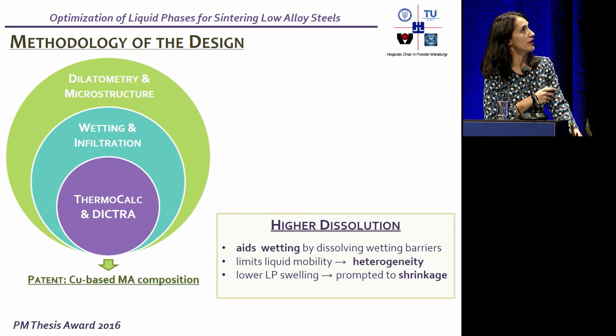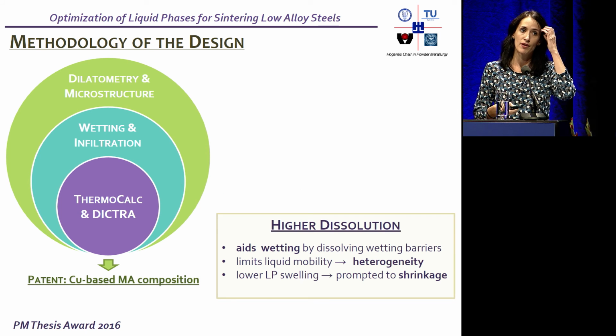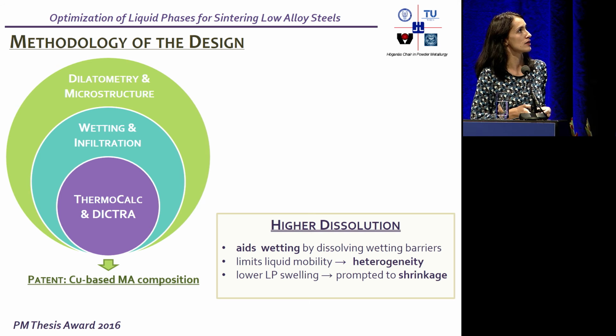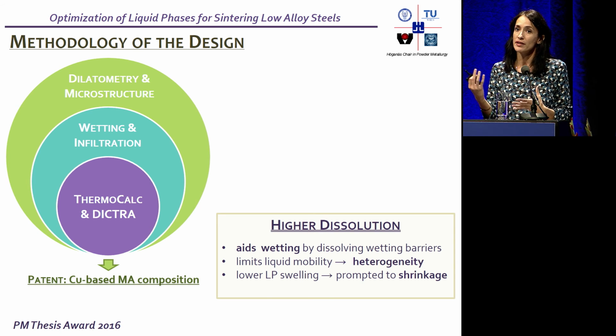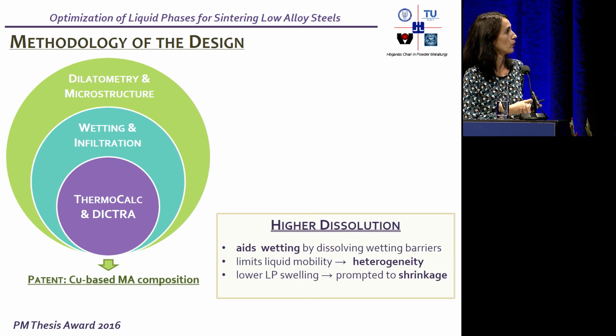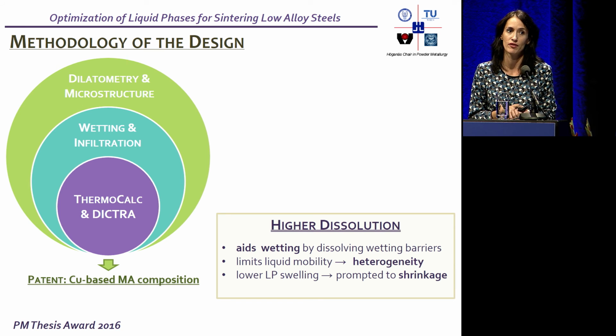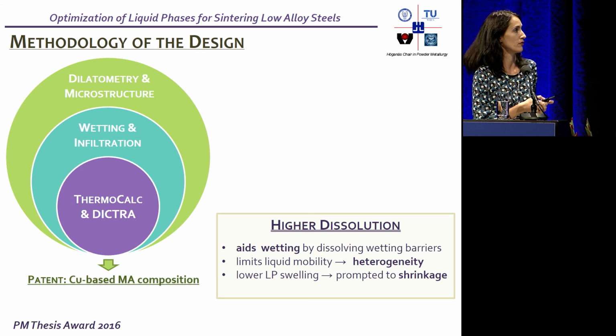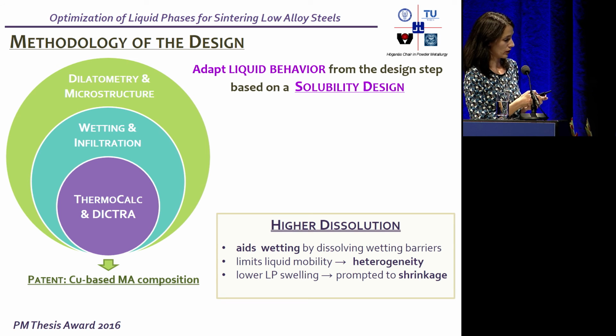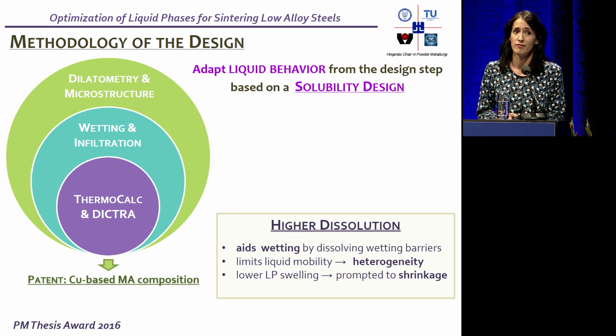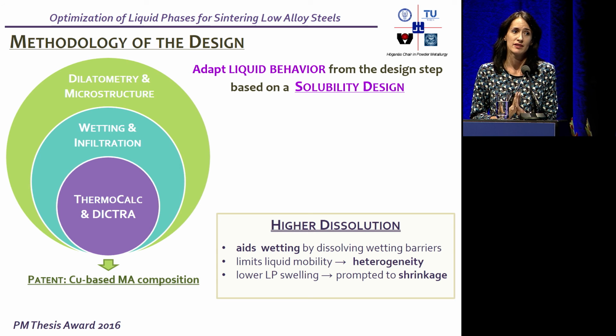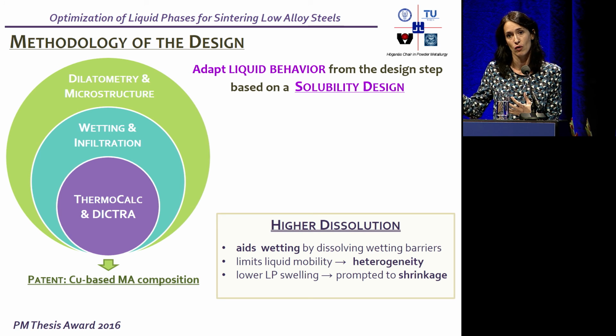So, in practice, what we have developed is a methodology of design of master alloys, taking into account this solubility from the first step of the designing of the composition. So when we are tailoring the composition of the liquid phase, we can also design the solubility condition between the solid and the liquid phase. This, of course, we will always experimentally validate, but what is important is that we can adapt the behavior of our liquid phase to the final requirements of our steel.